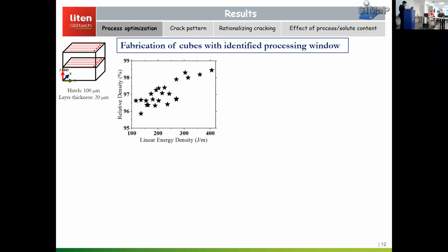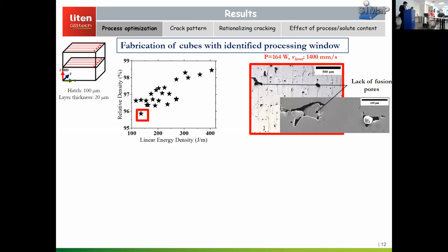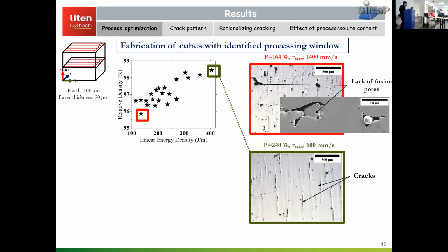So based on the stable processing conditions, let's analyze the density of the sample as a function of linear energy density. The density of samples increased as a function of linear energy density. For example, for low laser energy density, we can get microstructures having lack of fusion porosities. This is due to the lower linear energy density you are giving. And if we increase the laser energy density, we tend to decrease the lack of fusion porosities.